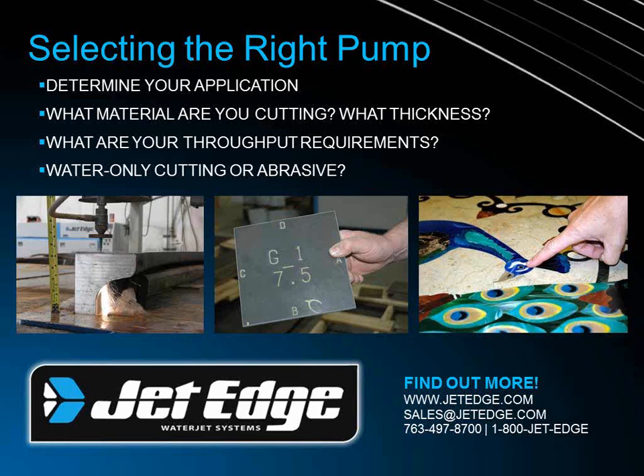When we say maximum separation cut speed, what does that mean? Maximum separation cut speed with an abrasive water jet is the definition of making 2 halves of a piece of material. So with my 10-30 nozzle combination, I'm going to remove approximately a 30 thousandths of an inch wide kerf at the entrance point of that stream, and I'm going to break out at my bottom side at somewhere around 18 to 20 thousandths. So I'm going to have approximately 10 thousandths of taper, or somewhere in that 5 to 10 thousandths of taper per side in that piece of material.